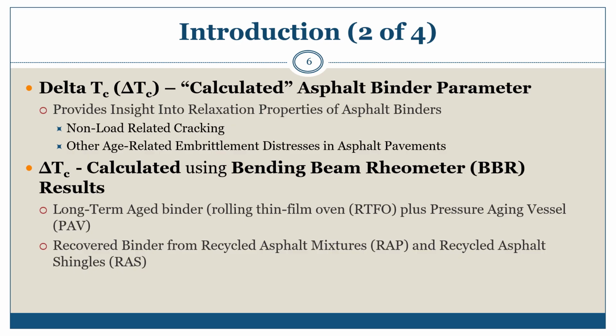It is intended to be calculated from data from asphalt binders that have been long-term aged, rolling thin film oven RTFO, plus pressure aging vessel PAV. Delta TC can also be calculated on recovered asphalt binders from reclaimed asphalt pavement, RAP, and reclaimed asphalt shingles, RAS, or in combination of these with virgin asphalt binder.